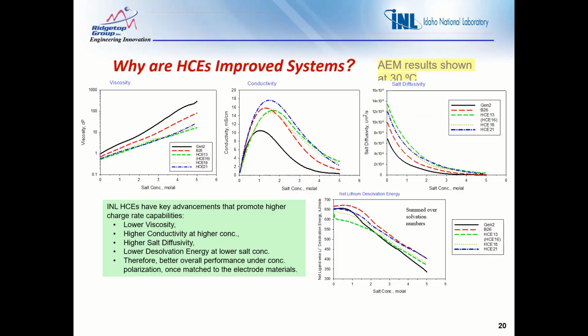If you're trying to do charging at rates like a 6C rate, which equilibrates to a 10-minute charge from an empty battery to a full one, you have to have something more than just low viscosity, because there are other factors that impact the success of that fast charge protocol. So in our case, we're looking at highly concentrated electrolytes, and this would be between 2 to 4 molal salt within the electrolyte. And because of that, you have advantages that emerge as you go to high salt concentration.